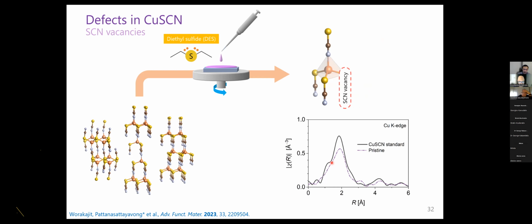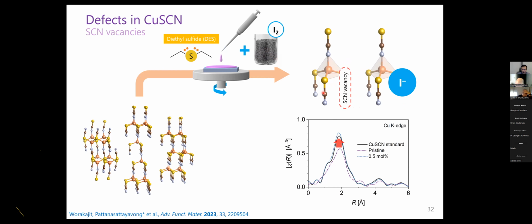And so we try to fill the defect states by using iodine. Iodine is very nice because it's also soluble in the diethyl sulfide. Just add the solid iodine directly into the same processing solution. And then we find that at the optimum condition as well, the local structure around copper is restored again.